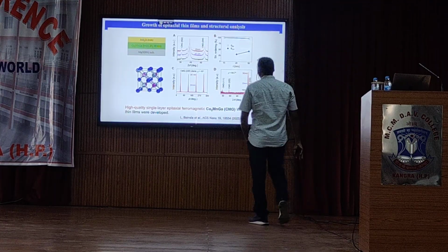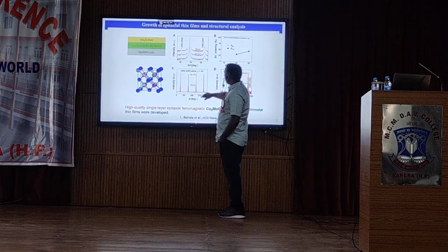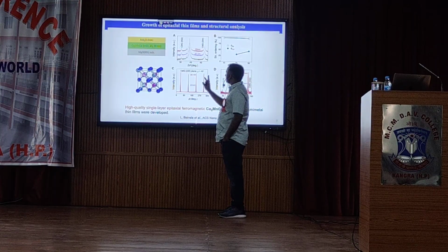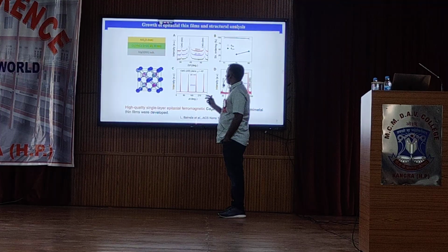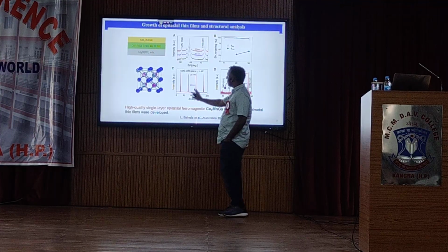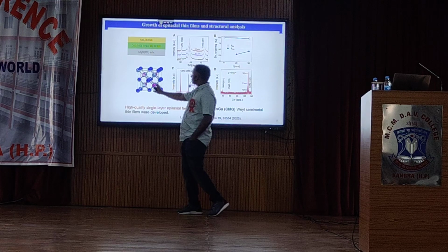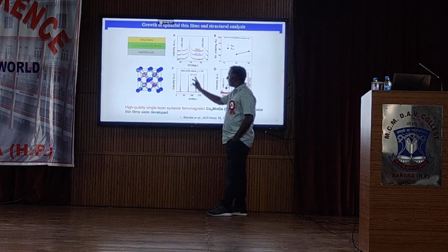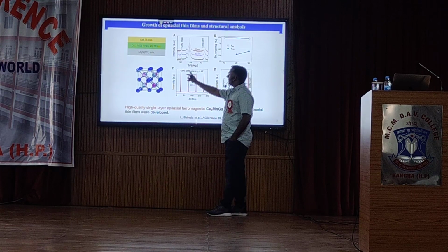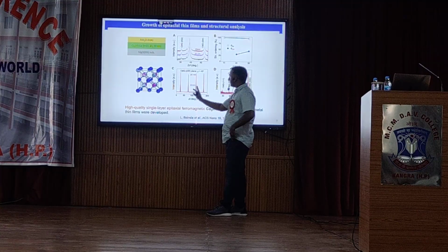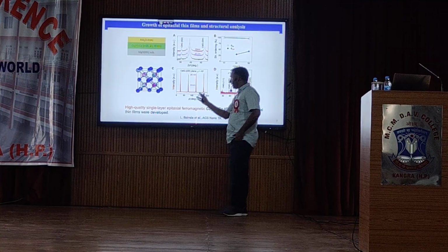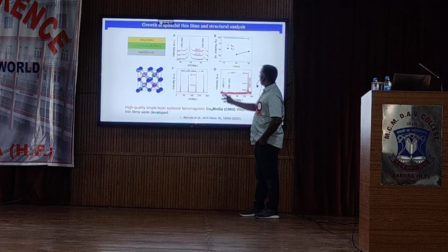here we also do phi scans of our thin films to confirm the symmetry. As you can see, very nice 4-fold symmetry. We have a cubic crystal, so for a cubic crystal we perform the phi scan for the fundamental 110 peak, and then we can see very nice 4-fold rotation symmetry, which again confirms the quality of the thin film.